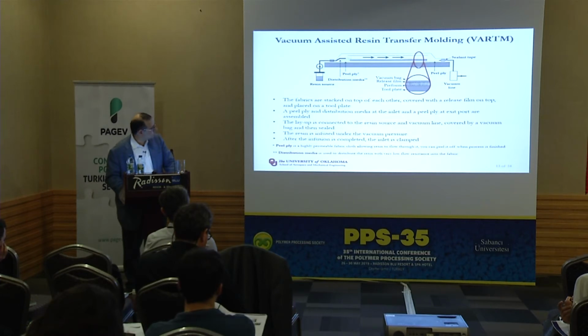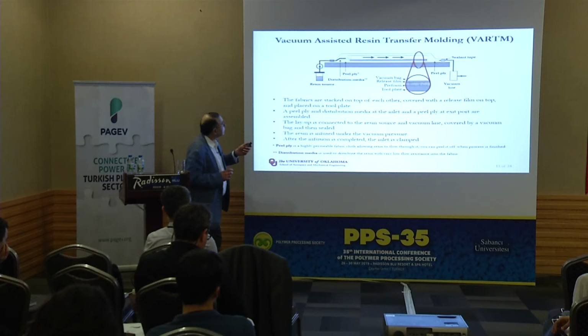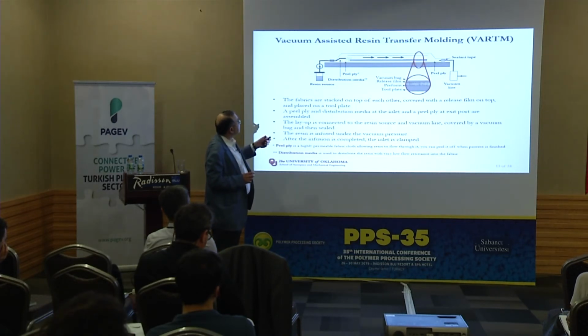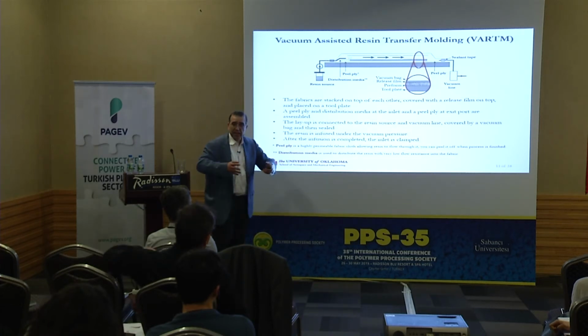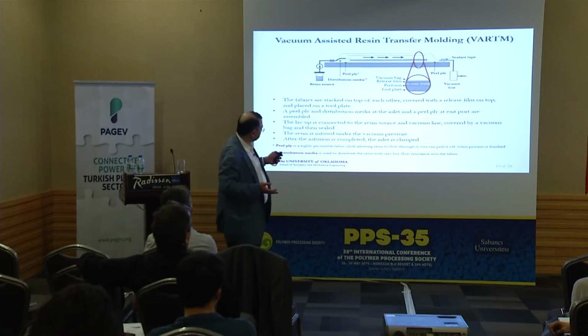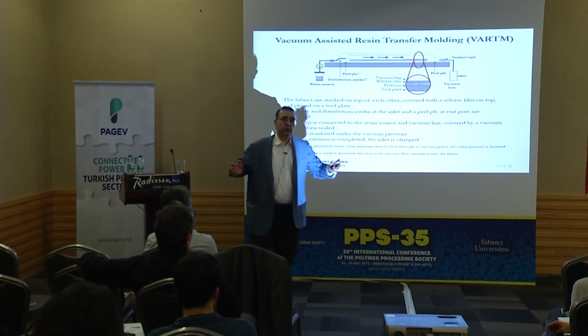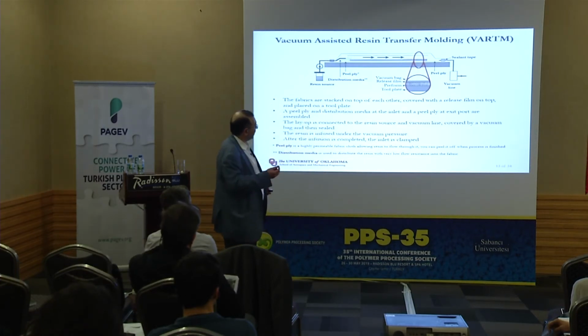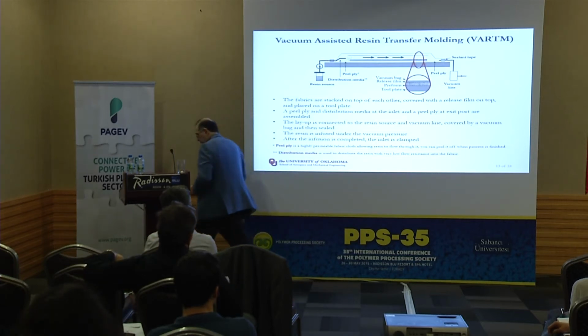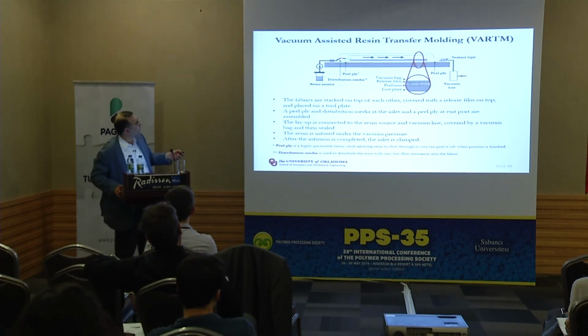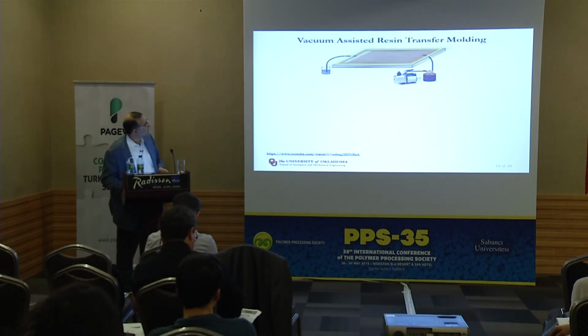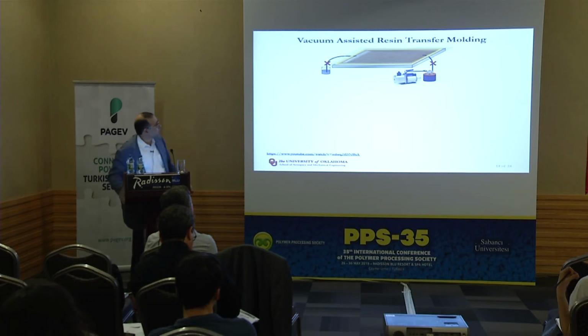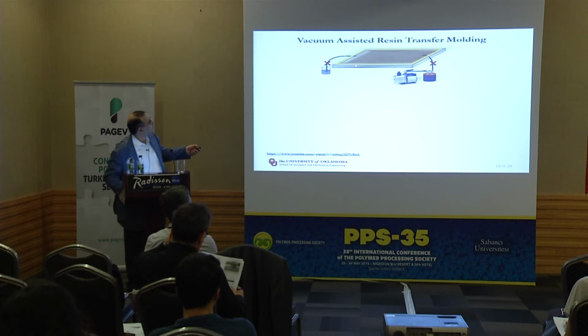On top, you can use distribution medium, or distribution media, this one here. You would have this resin inlet, and you don't want a really small point, you want the incoming resin to spread and then infuse and wet the fabric relatively fast. So you use so-called distribution media to distribute the resin early on. It's like a mesh with high permeability, and it makes the resin go fast. All right, so resin comes in, and then you close the inlet and you let the part cure. So this is the distribution media, so that the flow progresses in a uniform way.